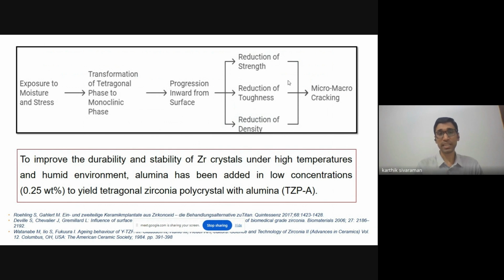So to improve the durability and stability, alumina had been added later, and this is known as tetragonal zirconia polycrystal with alumina. Now, in vitro studies have found evidence for aging, but they are found to be within the clinically acceptable limits. However, the concern for us is there are various manufacturers for zirconia, and most of them do not have a clear R&D. What I mean is the clear process of manufacturing and the conditions. So if you are using an implant from an unverified manufacturer, who does not provide data, you can have troubles later with the implant during clinical use.